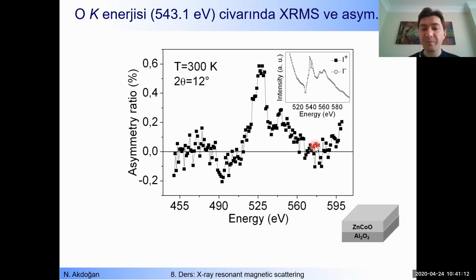If you remember, before cobalt ion implantation, here we have zinc oxide, right? And then we implanted that system with cobalt ions, and the cobalt replaced the zinc atoms, or this was the idea, okay? So if the cobalt atoms replace the zinc atoms, then there will be a relation between cobalt and oxygen atoms. So we can talk about cobalt-oxygen bonding, okay? Since cobalt is magnetic, it affects the oxygen P levels. Oxygen P levels are split due to the magnetic neighboring cobalt. Then we also see a signal from the oxygen.